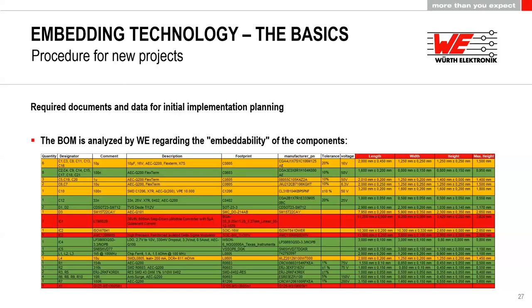And you see here, this is just out of a customer BOM, what we did here. In the last column, you see the maximum height, and there are components which are quite thick. So for example, IC1 is just too thick with its 3.6 millimeters, so we marked it red. And either it's being placed on the outer layer, or we find an additional package form which can be used here, so that this component might be used for embedding. But in the first point, we have to say no, IC1 does not work.